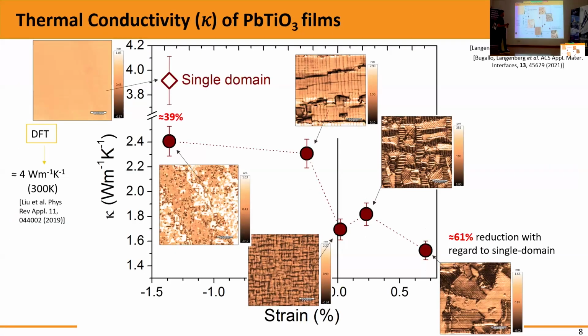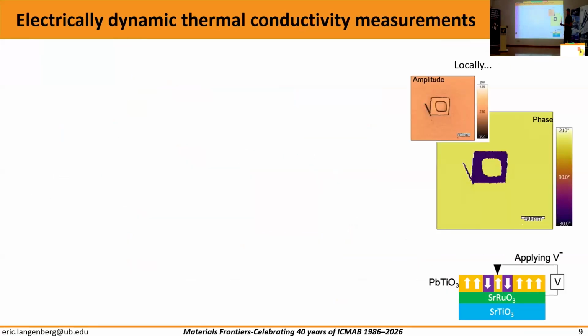And that's actually, years ago, we proved that in lead titanate, the density of domain walls matters. So I modified the density of domain walls in the lead titanate using epitaxial strain, and by changing the strain, you can change the density of the domain walls in your material. And then compared to a single domain in lead titanate, the thermal conductivity decreased significantly as we increased the density of domain walls. So domain walls scatter phonons. But the question is, how can we change them electrically?